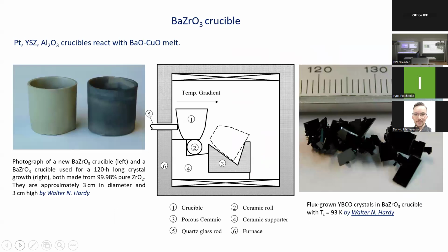And the main problem in flux growth is a strong reaction between all crucible materials commonly used for flux growth with barium oxide, copper oxide melt. And platinum contamination kills the superconductivity in these materials. Aluminum contamination practically doesn't affect TC, although aluminum sits on the copper site, and it might affect other